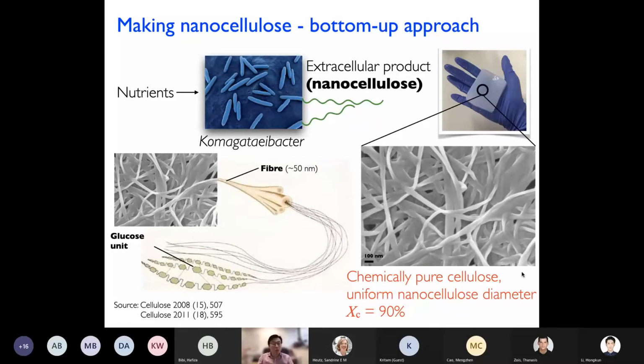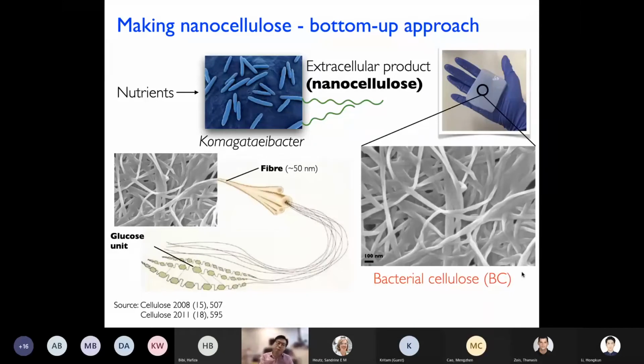Very, very crystalline, 90% degree of crystallinity as far as we can measure. There are hypotheses that confirm that most likely bacterial cellulose is 100% crystalline. So there's still quite a big dispute there on the crystal structure of cellulose and cellulosic materials. In any case, we shall now refer to nanocellulose synthesized by bacteria as bacterial cellulose today.